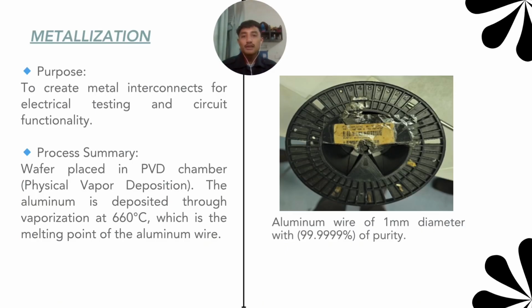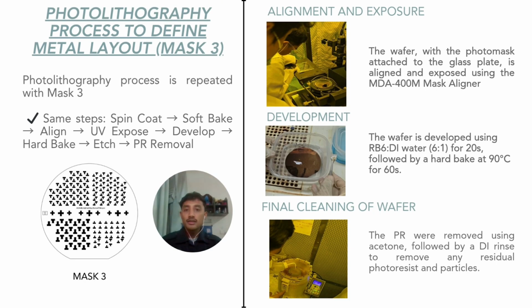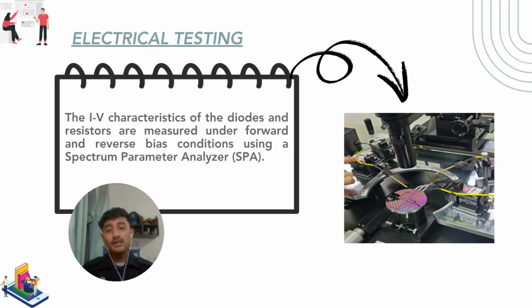Moving on to the final process, which is metallization. The wafer is placed in the PVD chamber and aluminum is deposited through evaporation at 660 Celsius, which is the melting point for aluminum. Then we do the same photolithography process to define the metal layout using a mask. Right after that, the photoresist is removed using acetone and we clean our wafer using water to remove any remaining contaminants. Finally, we did the electrical testing on the resistor and diode fabricated on our wafer using a semiconductor parameter analyzer to define the IV characteristic.